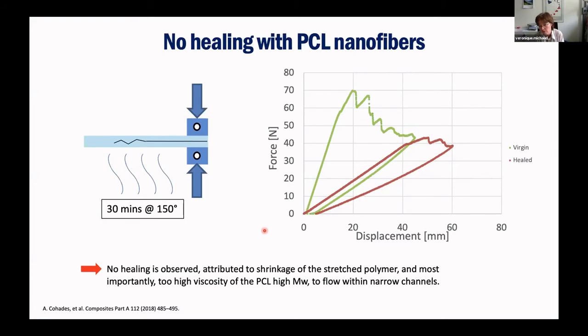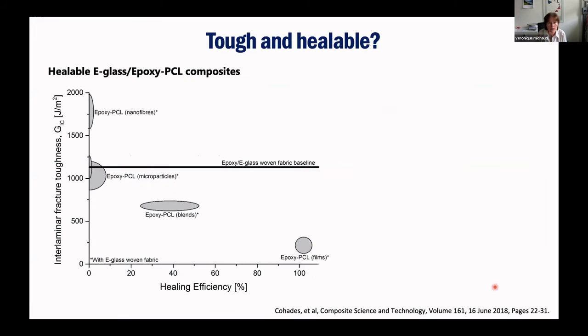Also, the viscosity of the PCL that we used for making these nanofibers was a bit high, so it wasn't really flowing in these narrow channels that we had. So we understood why, but at least it was not so great. So the next step was to say, okay, what can we do? And this was in 2018 or something. Amael progressed in his PhD thesis, and we said we have this situation. If we use nanofibers, we have a great toughness, but zero healing efficiency.